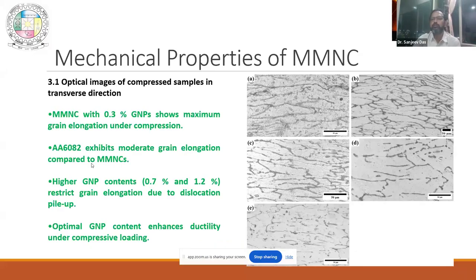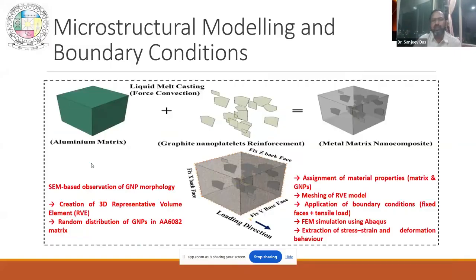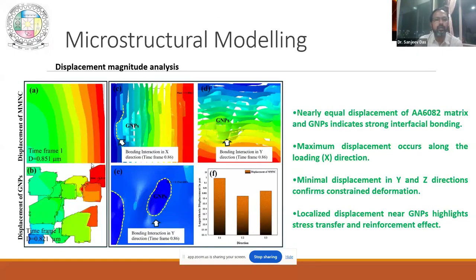So these are again the sectional images. Here also you will get elongated grains. Those were vertically elongated; this is horizontally elongated grains, and deformation is occurring in both the shapes. We did some modeling. The modeling part is basically done by my students. Most of my students are mechanical engineers. I am not very good or expert in modeling. So they tried to understand why the grain size is decreasing. To understand that, they did the modeling, and they found that the GNPs are basically blocking the movement of the grain growth. So that is what we understood from the modeling part, that the grain growth can be restricted by these nanoparticles.